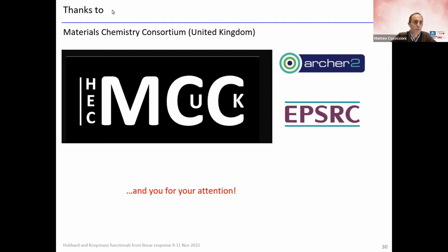Then, of course, there is this problem of multiple local minima that your system can get with when using finite Hubbard U and V's, and there's always a chance that the global ground state is something else than what you're looking at, but at least you have somewhere to start your investigation. I don't know, Yuri, if you want to add something. I totally agree with you.